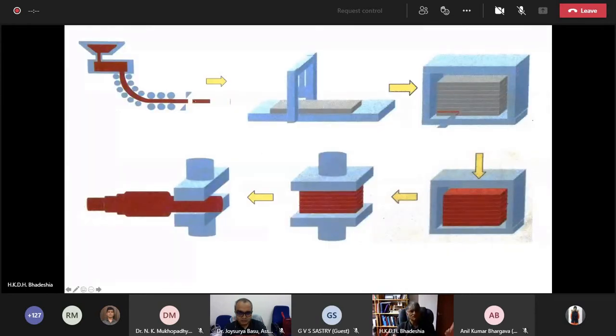Well, you continuously cast the steel as normal, and you cut it up into chunks. You stack the chunks up in a vacuum, and you then make welds between the plates. You then forge them together, and rotate. The forging can even create circular components. And this is our rotor. So by doing this, you cut down any effects of long-range segregation. And the pictures that follow are real pictures of massive components made in this way to avoid segregation.